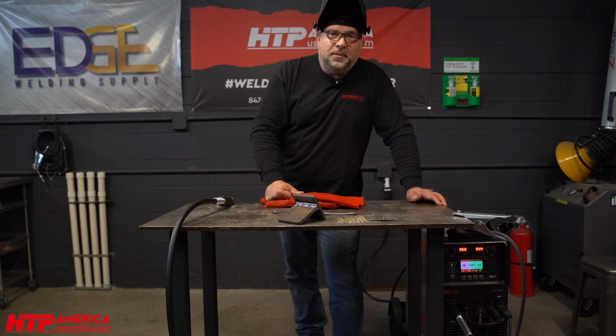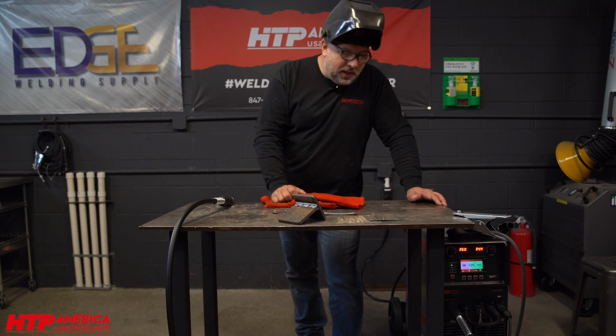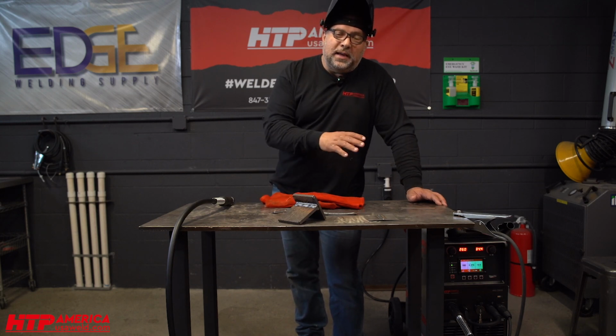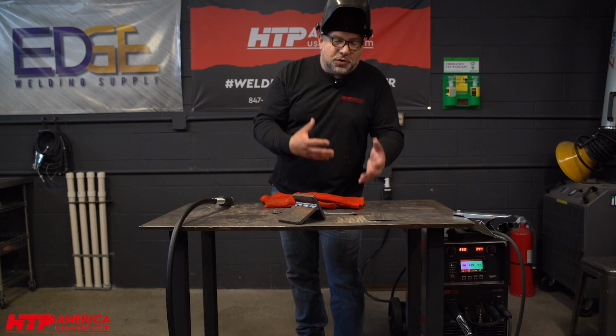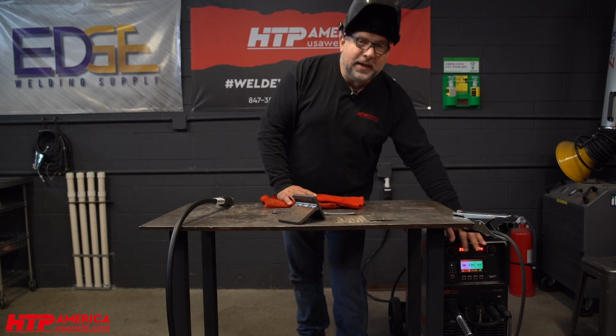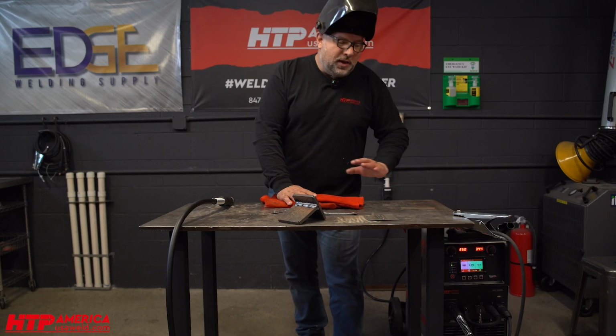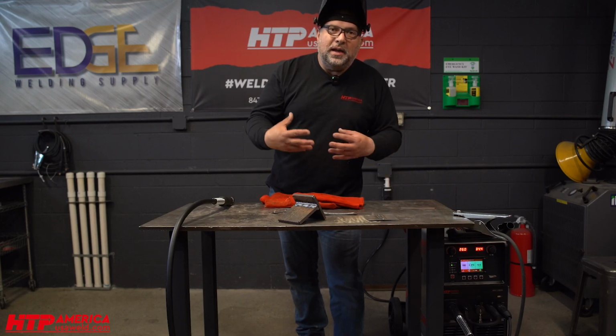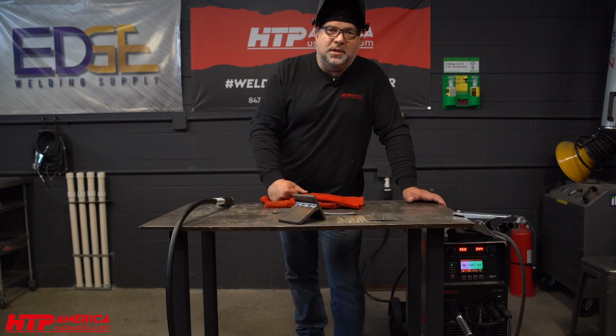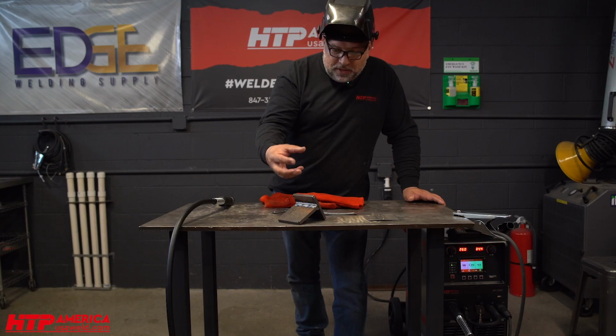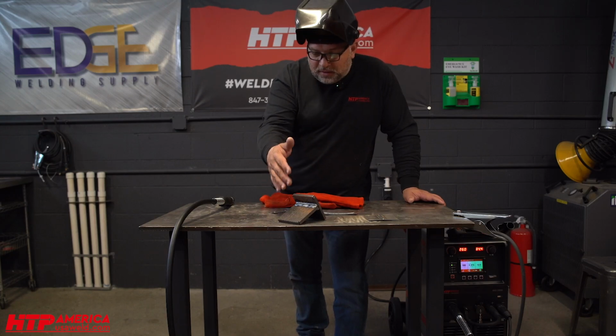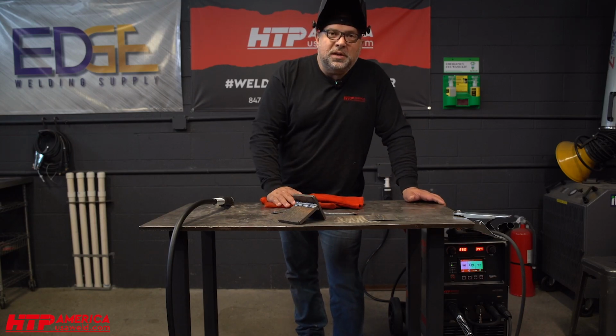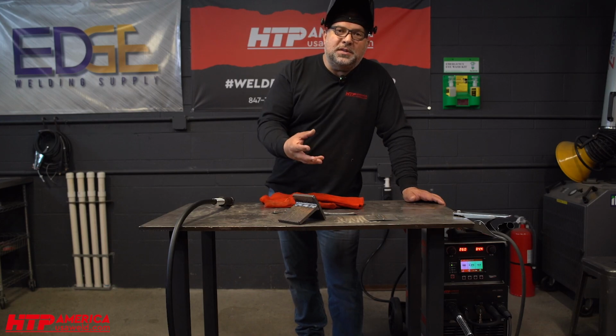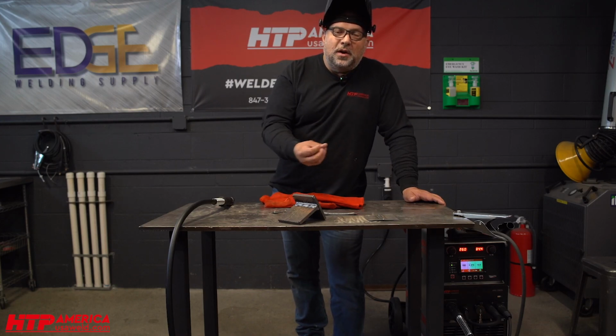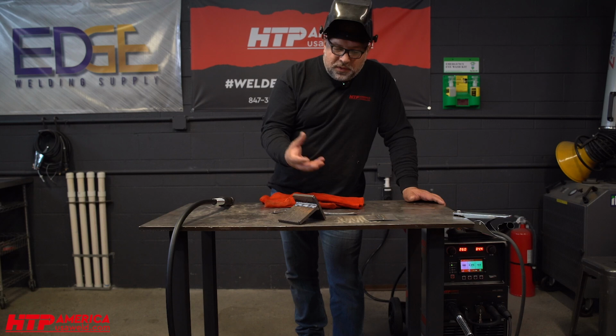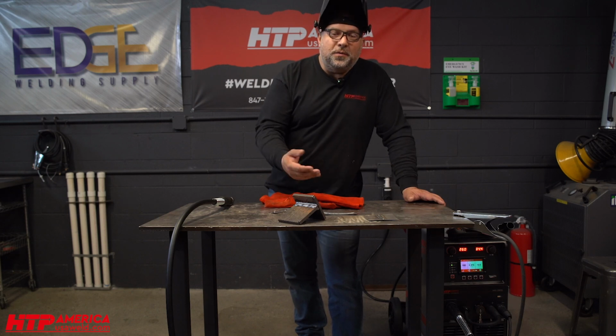That sums it up. You'll like the way it welds or you won't. If you don't like it, if you're more that short circuit transformer guy, go back in the manual mode, go by the door chart, and you will have the sound and the way it welds like you have been used to. If you want to get deep penetration in material that is maybe a little bit cruddy, had some surface rust or some mill scale on it, and if you're in a situation where cleaning is either not possible or not cost effective and you still want to weld, there you go. That is your solution.